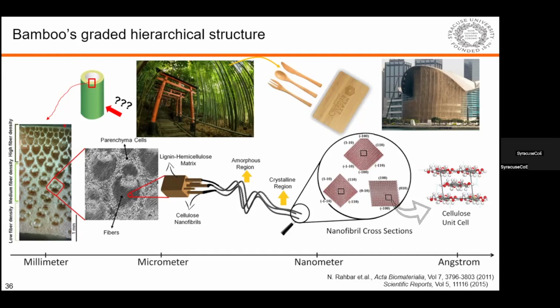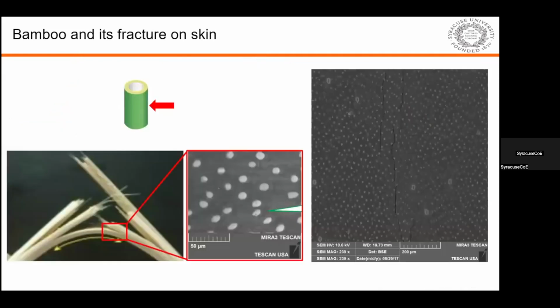And then if you check the outermost surface of bamboo, interestingly, it's not just cellulose, but there are a lot of silica particles. These silica particles get embedded into the surface of bamboo and make this bamboo surface strong. If you use your knife to hit bamboo, unless you use very large force, it won't easily create a crack.